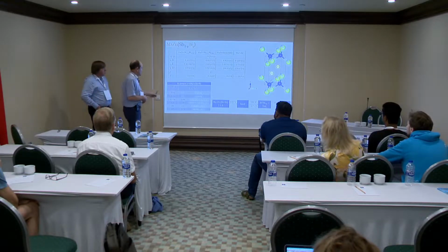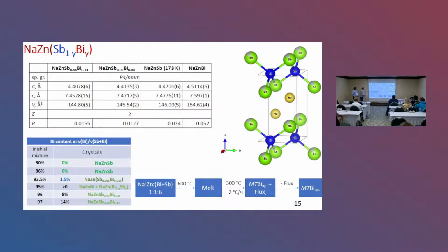This is a very big difference between the initial compositions and the composition of the crystals. We can see that antimony goes to the crystal. All antimony from the melt goes to the crystals. This is a problem, but we may prepare crystals if we take a very large amount of bismuth and a small amount of antimony. Okay. Yeah, thanks.